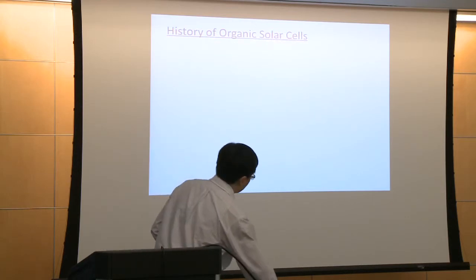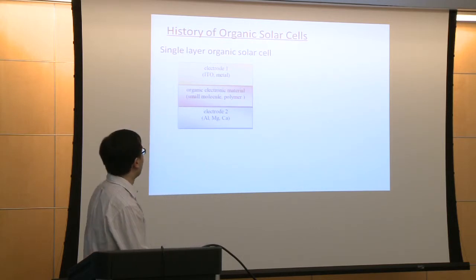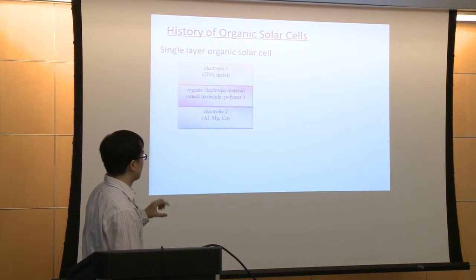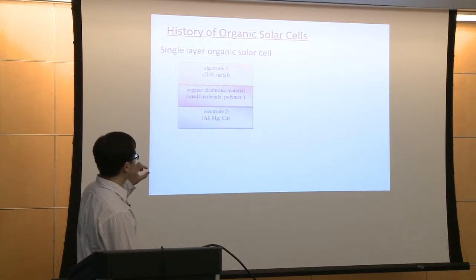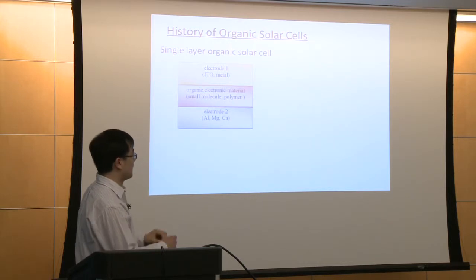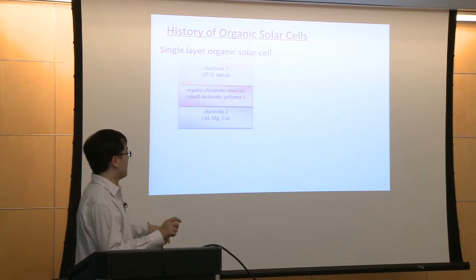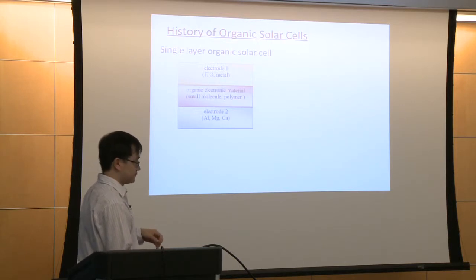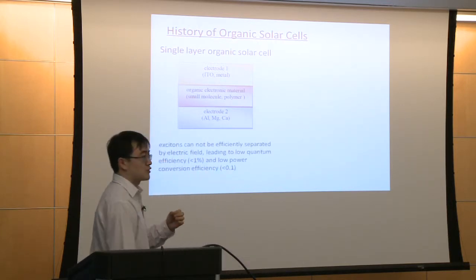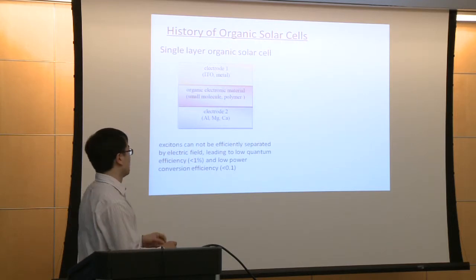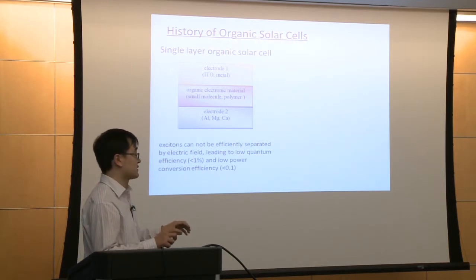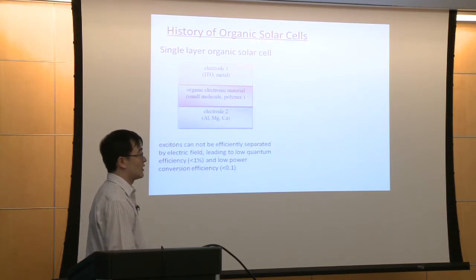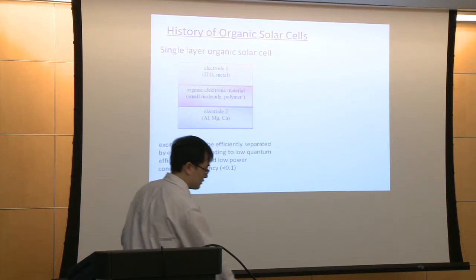So there are almost 50 years of organic solar cell development. The first generation of the organic solar cell is called the single layer organic solar cell. There's just one layer made of organic electronic material between the two electrodes. Under the effect of the electrical field between electrode 1 and electrode 2, they try to split the excitons generated by the absorption of light. However, because the electrical field is not strong enough to efficiently separate the excitons, the quantum efficiency and the power conversion efficiency are very low compared to the silicon solar cell.